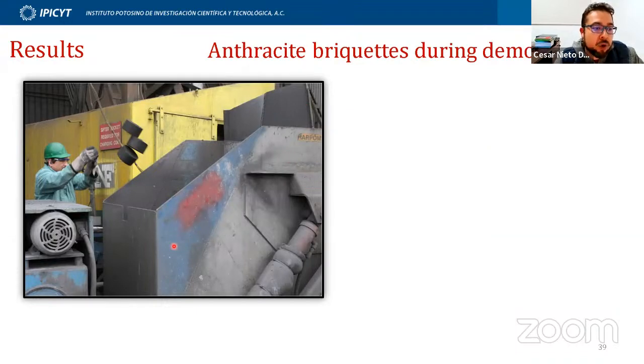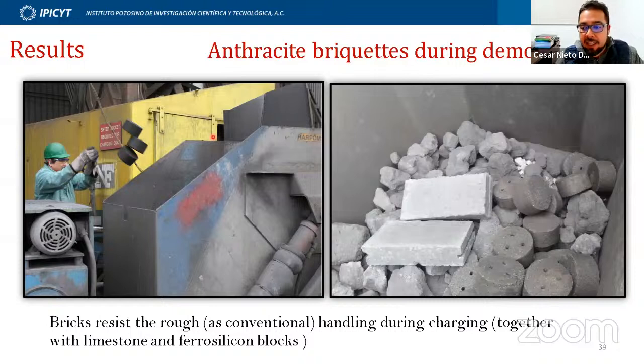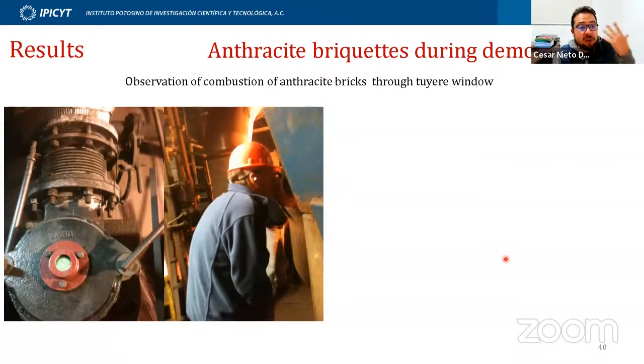Here is a picture of the loading charge car. This is a car that goes all the way to the top of the furnace. And this is just some personnel of the company that were charging these anthracite briquettes. And you can see here is the charging load. Here is the coke, here are some iron silicate alloys, and here are the anthracite briquettes. And you can see that they survive this very rough handling during loading.